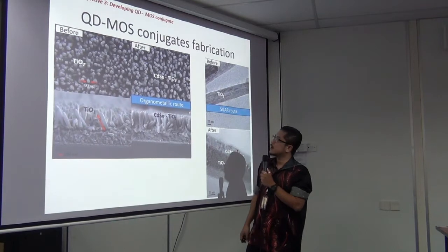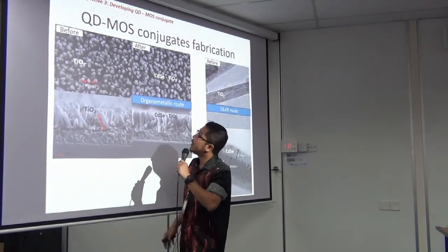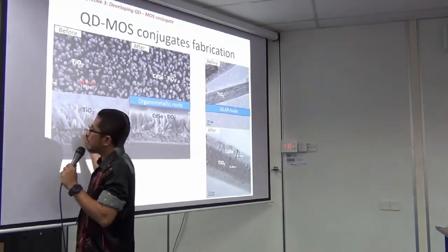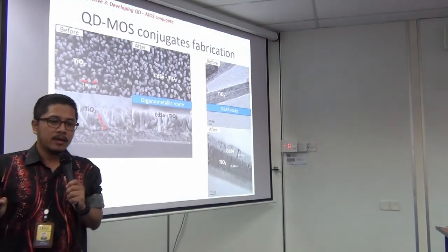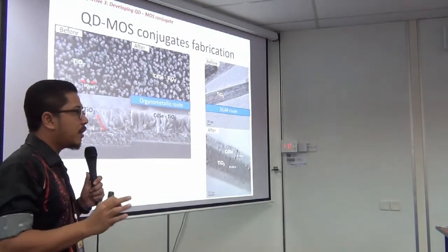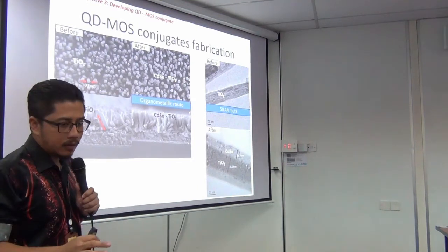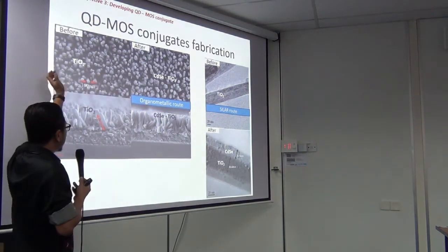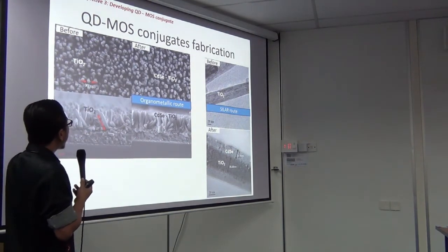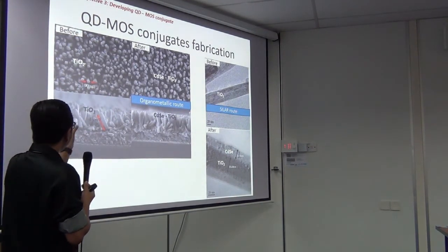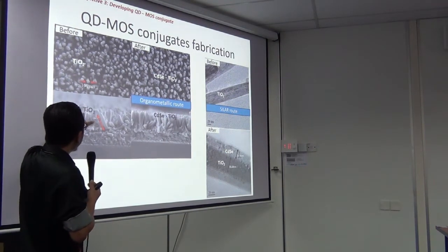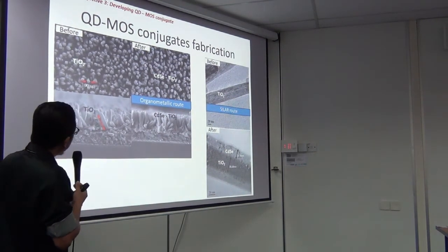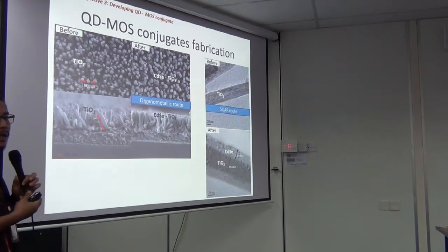Let's see the figure over here. These are the TiO2, or the metal oxide semiconductor, which we fabricated using the hydrothermal method. And the structure is nanorods with a length of about 1 micrometer, and the width, or diameter, of the nanorod is about 200 nanometers.